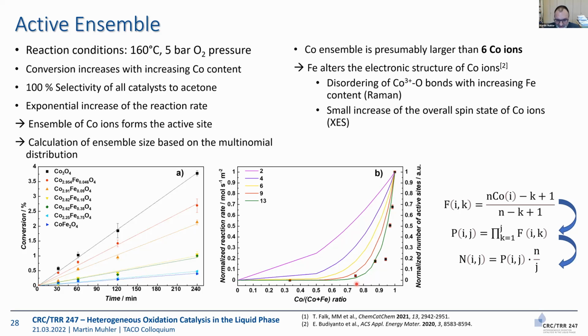which is quite surprising. And one way to analyze this data is now we assumed that we need larger cobalt ensembles that form the active site. And when you do a mathematical analysis, these are these straight curves in here, then you can estimate that this cobalt ensemble is actually larger than 6 cobalt ions. And that would be one of the few ways how to explain that adding just a little bit of iron has such a strong catalytic influence, because then iron lowers the size of these cobalt ensembles.